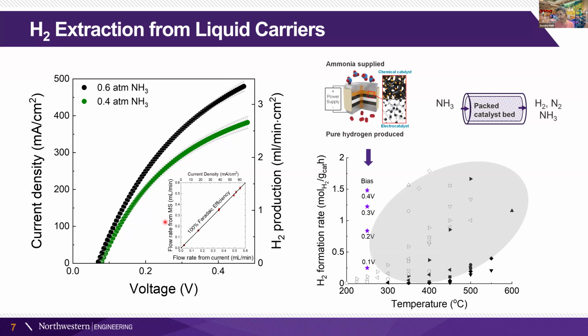And in that case, because the residual ammonia is still combined with the hydrogen and the nitrogen, you then have to follow that with a hydrogen separation, hydrogen purification step, whereas in the electrochemical process, the hydrogen is already pure. There's no residual ammonia in it.